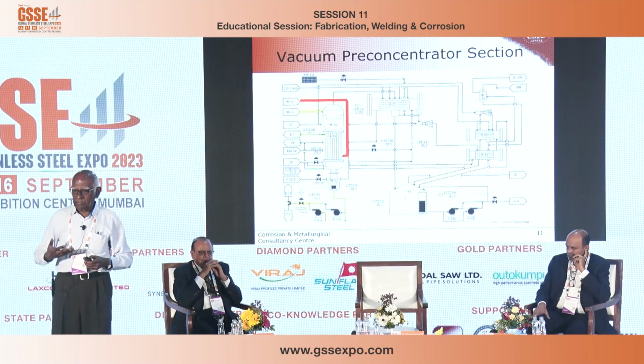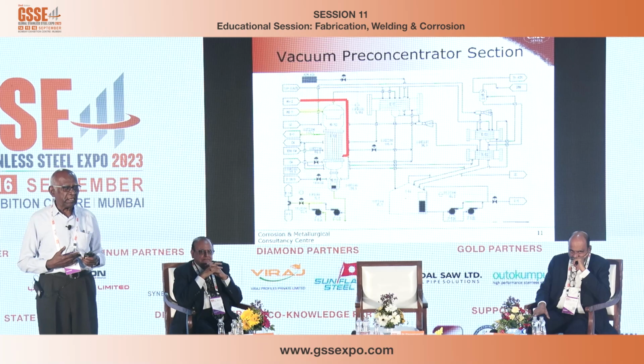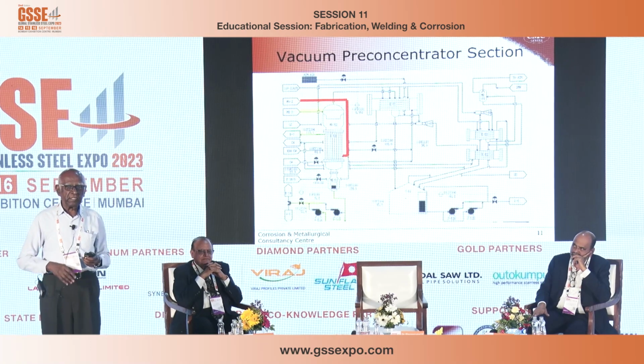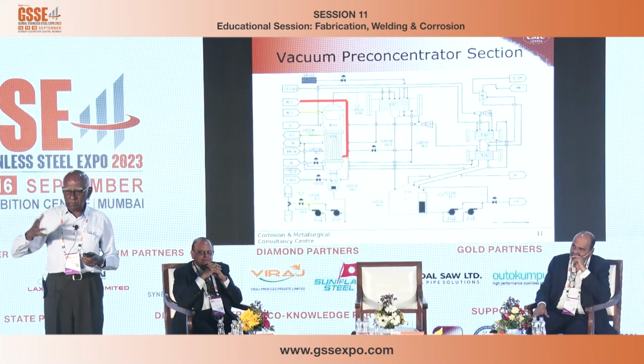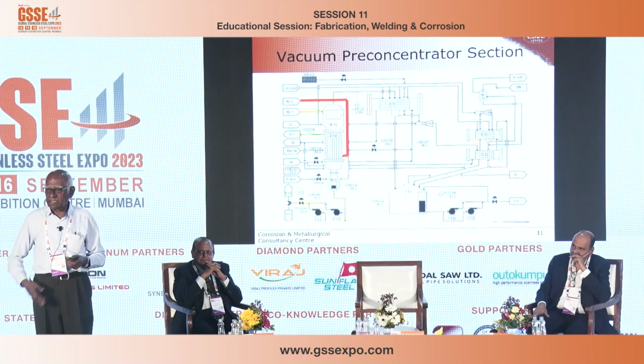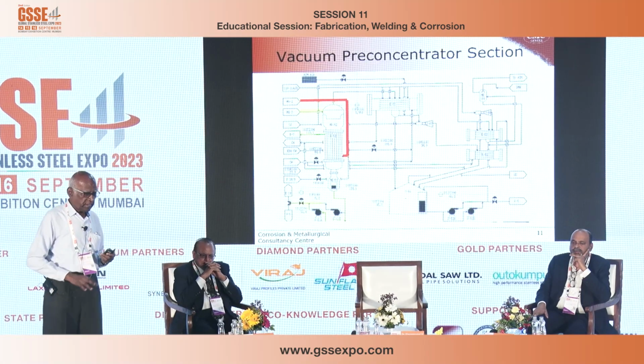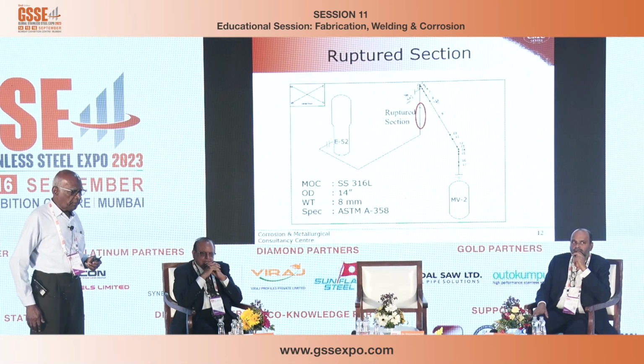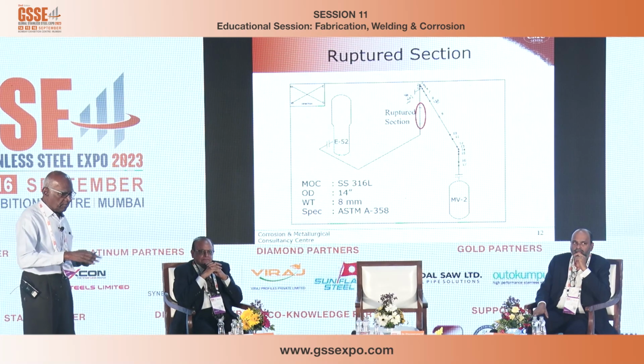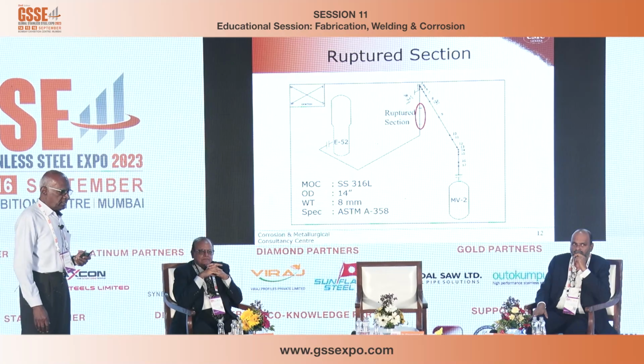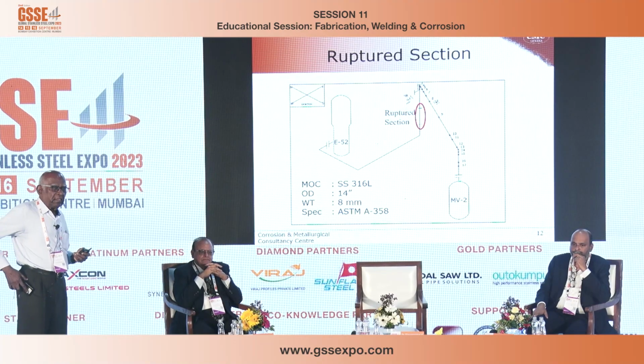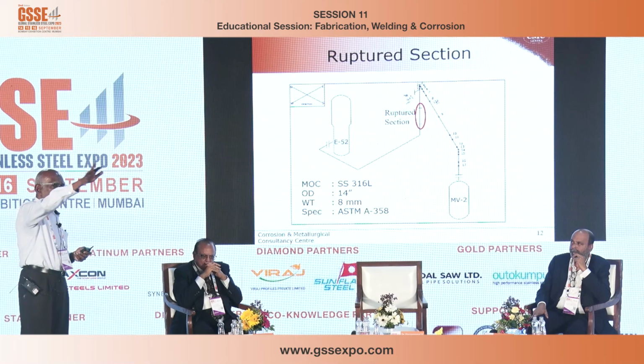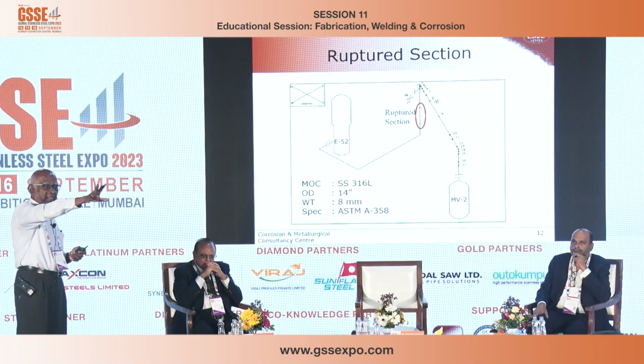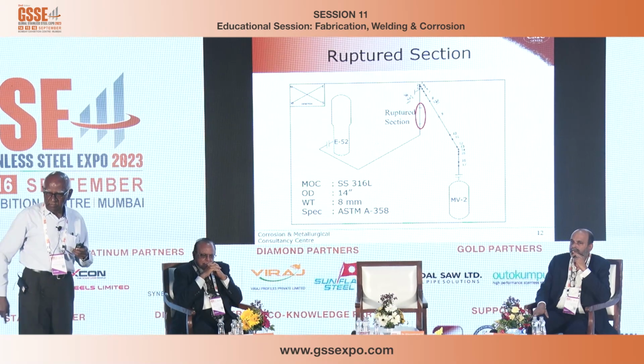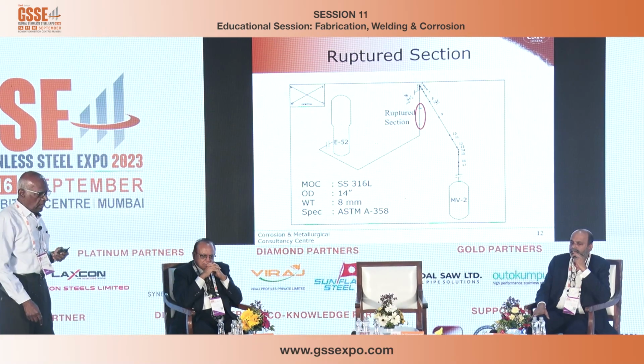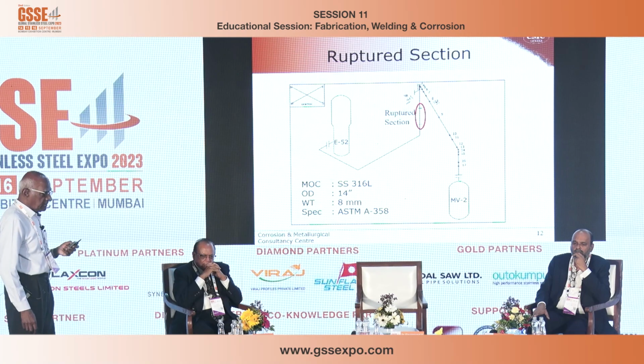Even though the plant was designed for very high pressure. Fortunately, it was an automatic plant. Nobody was injured, unlike Bhopal, where suddenly a pipe burst, killing so many people. But here, nobody was injured. You can look at the stainless steel pipe, and this is a little detail. At the bottom, it's a 316 stainless steel. If you go through all the pavilion, 90% of the shops talk about 316L stainless steel. It is 14-inch diameter and 8 mm thickness.